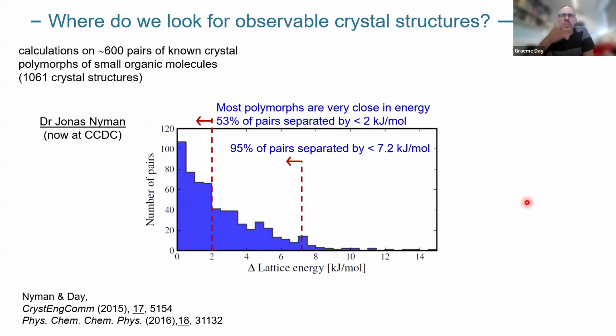And we informed these with studies we've done over the years. This was work done by Jonas Nyman, who was a PhD student with us in Southampton, now works at the CCDC. What he did was he took lots of pairs of polymorphs, known pairs of polymorphs from the Cambridge Structural Database, and he evaluated energy differences between those polymorph pairs. And what we were interested in there was to get an idea of what is the possible range of energy differences between polymorphs. Because if we assume that the lowest energy crystal structure from our predictions will always correspond to an observable crystal, then this range of polymorph energy differences tells us how far up the landscape we expect to have to look for potential polymorphs. So it tells us where to focus our efforts when we're looking at these structure prediction landscapes.